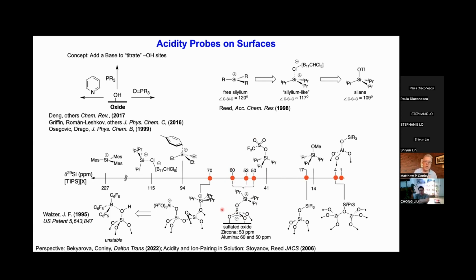If you try to engineer something that's more weakly coordinating, and we did that by reacting Ingo Krossing's strong Lewis superacid with silica dehydrated at 700, followed by reaction with a silane reagent to generate the sililium-like ion pair, we can even push further down towards these sililium-like ions. And I think using this methodology of thinking about ion pairing in terms of your silicon NMR chemical shift is a way to open up how to handle ion pairing on surfaces from that organometallic perspective.